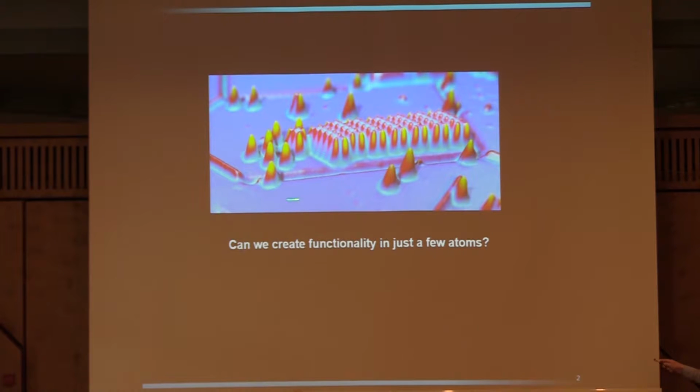So you're looking here at a 3D rendering of an STM image. All these atoms are iron atoms that we assemble on the surface, and the surface now is a copper crystal where we grow by self-assembly one monolayer of copper nitride on it. And the copper nitride in bulk is an insulator. In this one monolayer, it is still metallic, but it serves the purpose of sort of keeping the magnetic moments of the iron atoms intact.